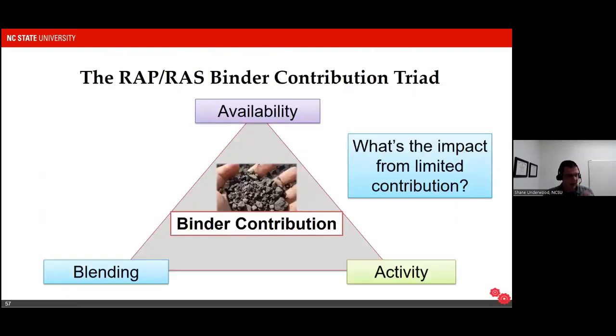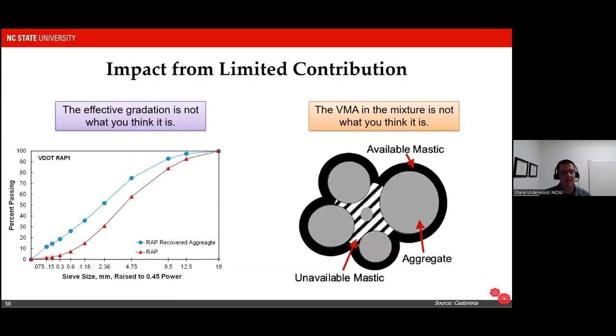Now, the last thing I want to mention here today is, what is the impact if we do not get good contribution from the mixture? Now, this is work, again, that Dr. Castorena has been looking at quite a bit. And what she's been able to devise is a methodology to design the mixture so that we better leverage known contribution levels. She has developed a technique where she can create or identify the availability of the asphalt binder and adjust the gradation in a way that gives us a similar voids in mineral aggregate. And as a result, we can actually see improved performance by carefully engineering the asphalt mixture, taking into account that not all binder contributes to performance.